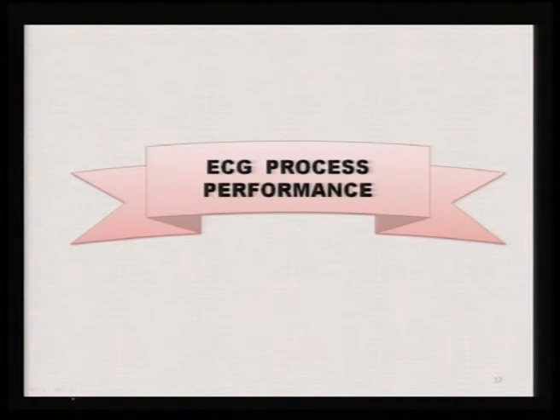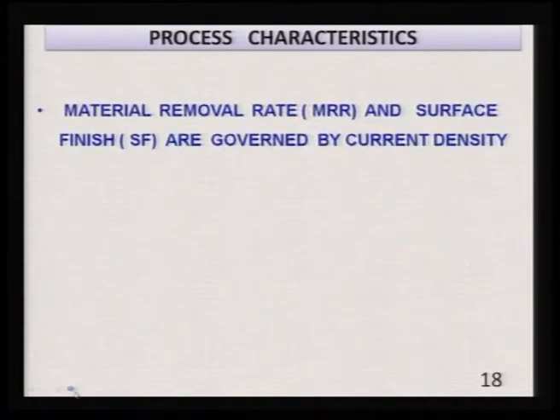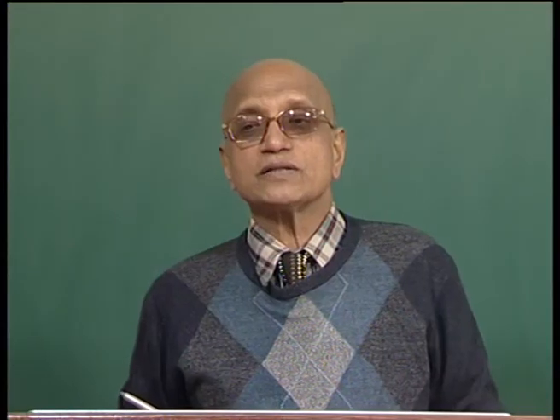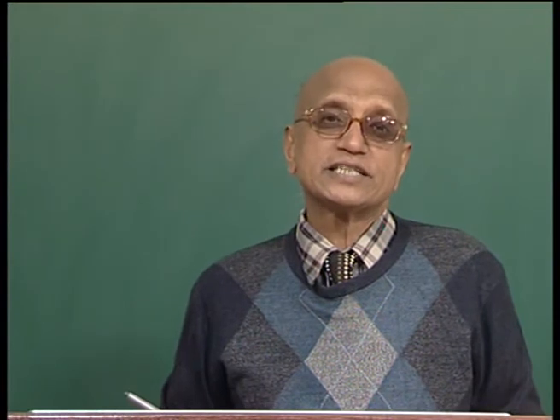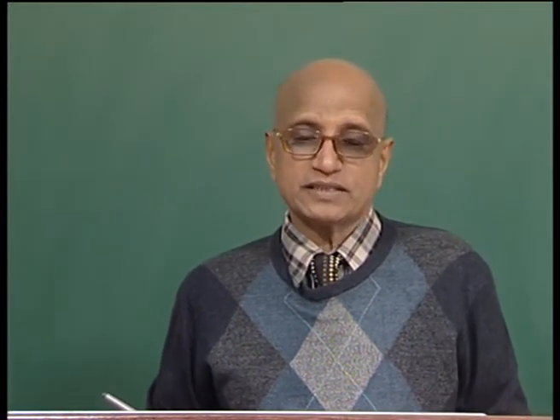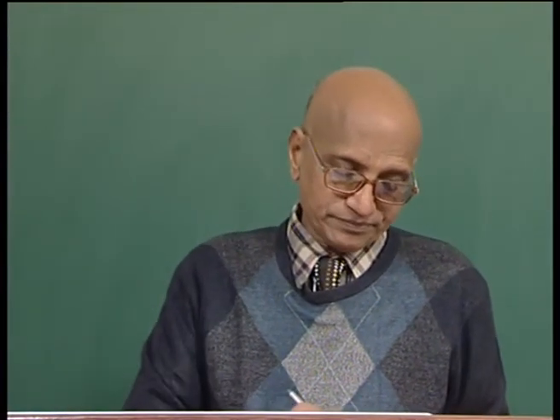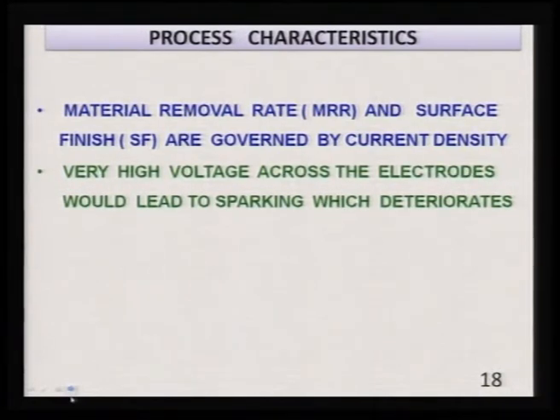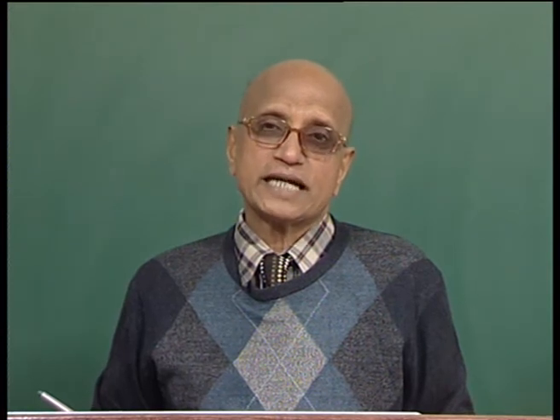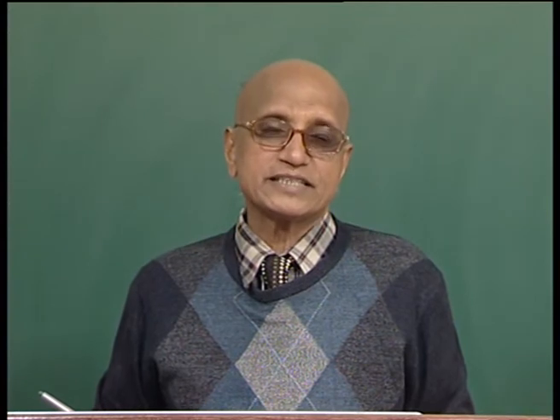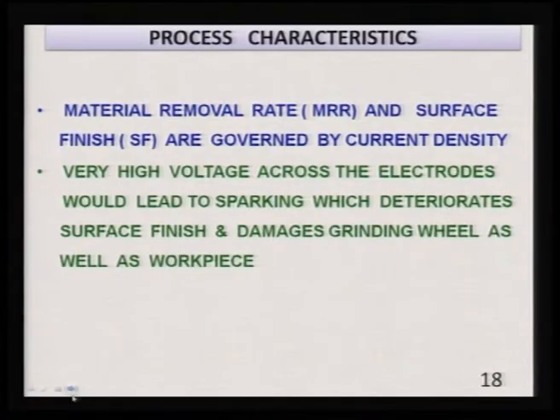Now, electrochemical process performance. Material removal rate and surface finish are governed by current density, as in case of electrochemical machining, because as I have mentioned, 90% of the total material removed in electrochemical grinding is due to the electrochemical dissolution. That means, current density is going to govern the material removal rate. Very high voltage across the electrodes would lead to sparking. So, we should not use very high voltage between the two electrodes, that is the grinding wheel and the workpiece, otherwise sparking will take place, and this sparking will damage the grinding wheel as well as workpiece both, and it is undesirable. It will deteriorate the surface finish also.